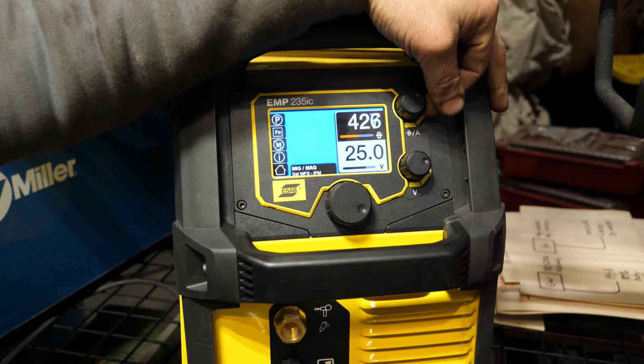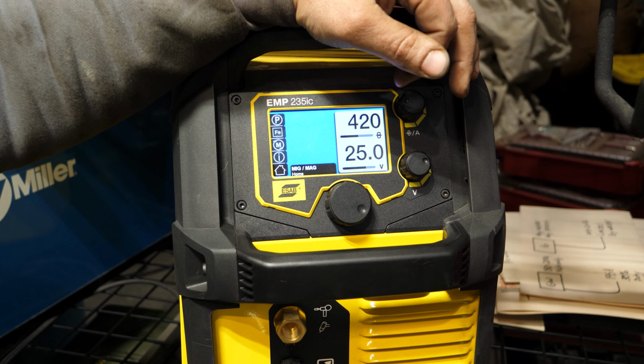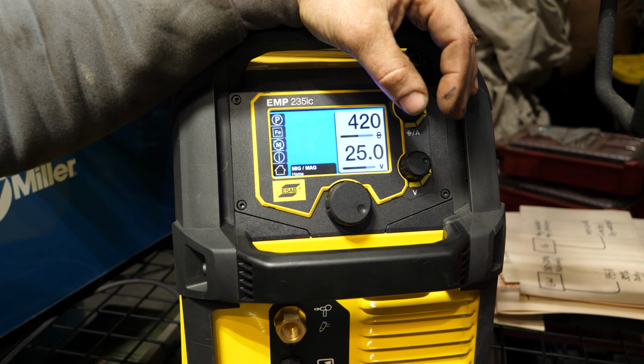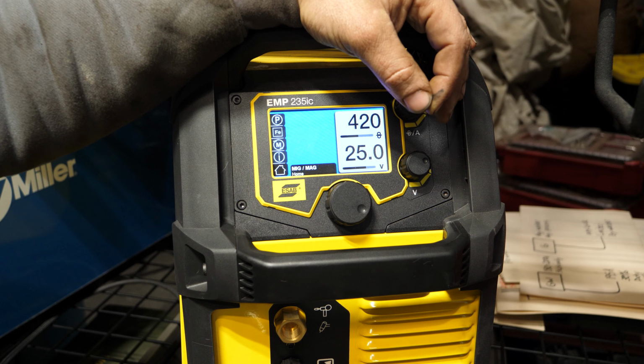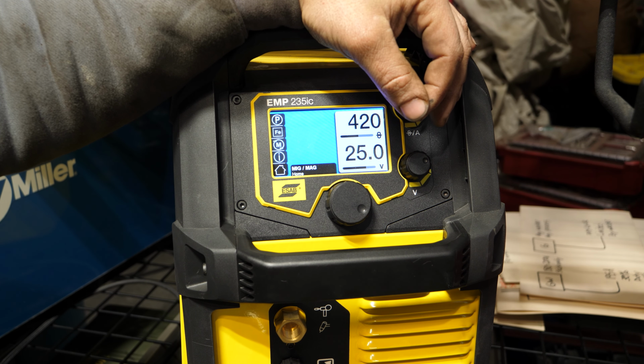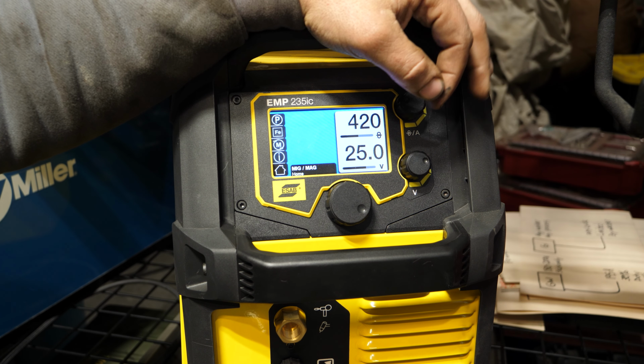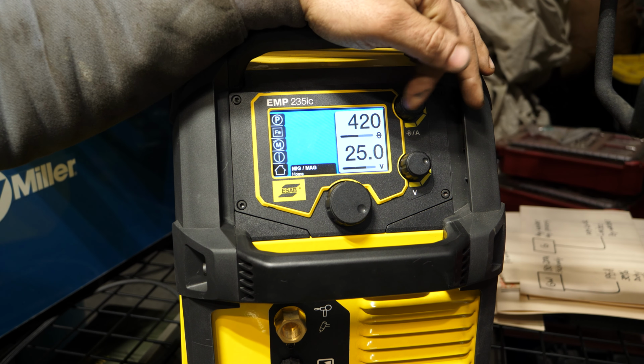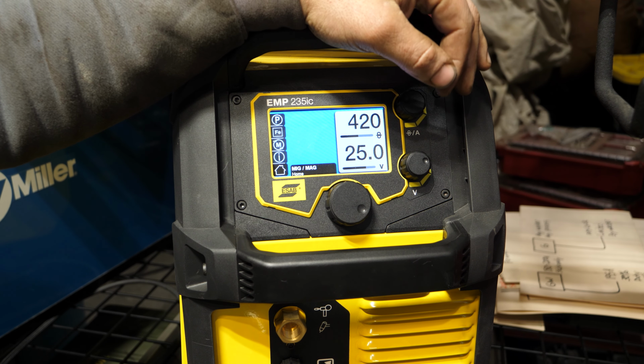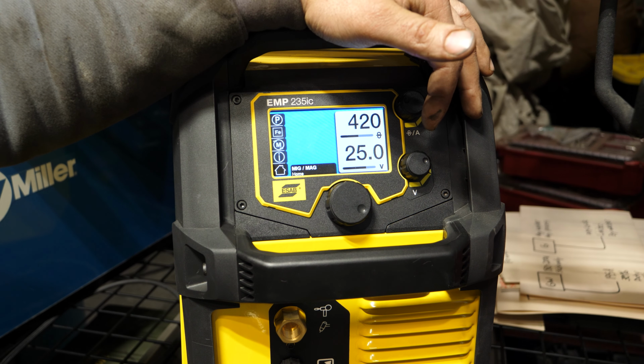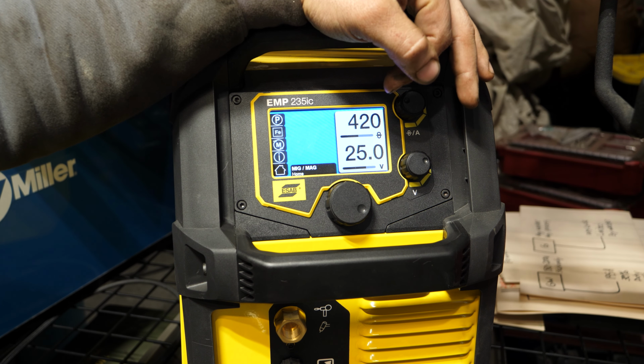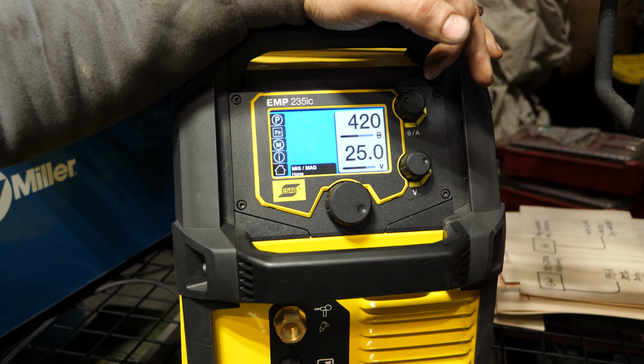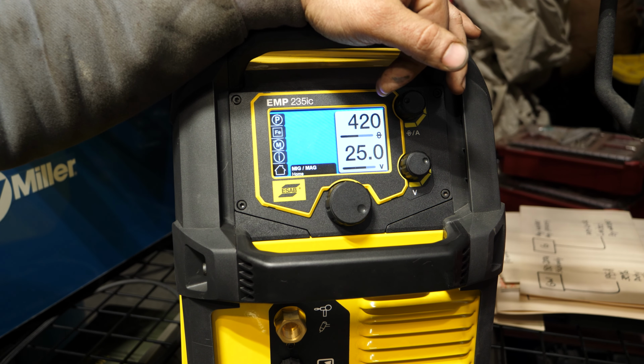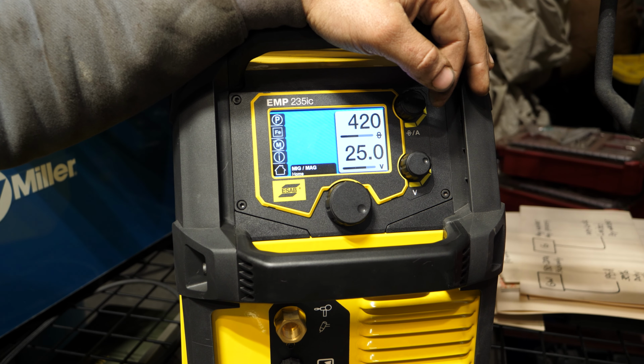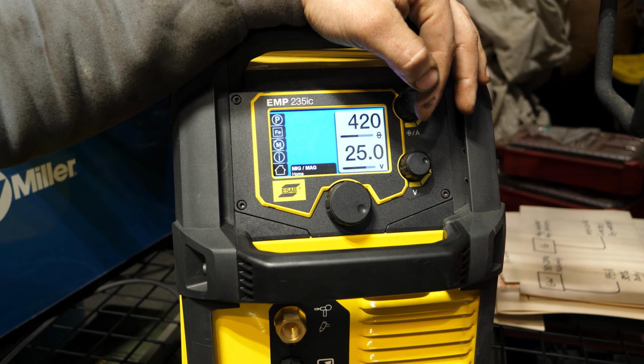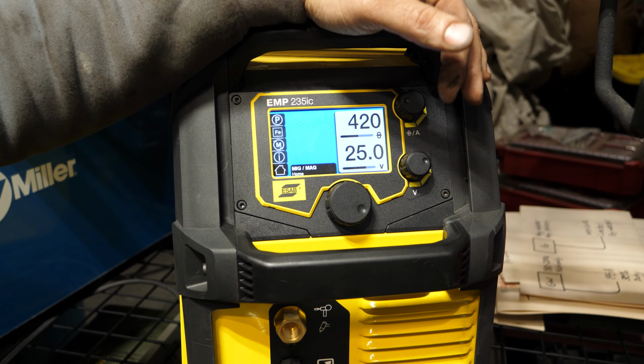And the reason for such high wire speed is because when you're running 25 volts, an arc will exist between the molten puddle and your metal and the contact tip. And you're liquefying the wire because it simply can't handle that much heat input. Well, if your wire feed is too low, what will end up happening is you're almost going to be TIG welding with your contact tip to the plate. You're going to have an arc that exists and it's going to start consuming your contact tip or fuse the wire to your contact tip in a burn back situation. And by cranking the wire feed up, that essentially keeps that from happening. It keeps the arc arcing off the wire for the instant that it does in order for it to not burn the contact tip up.